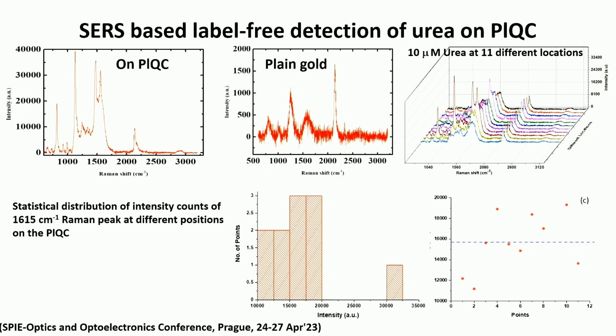This is surface enhanced Raman scattering from these structures. We showed label-free detection of urea. This is on a plasmonic quasi-crystal. On a PLQC, this basically gives enhanced SERS signals compared to the plain gold samples. I'll show in the next slide that we can go up to attomolar sensitivity of detection in this case.